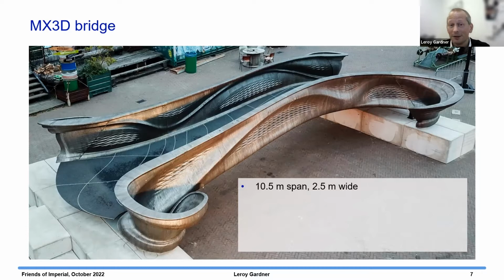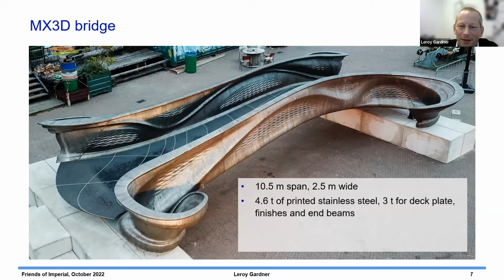It's a footbridge. It's 10.5 meters span and 2.5 meters wide. There's about 4.6 tons of printed material. It's stainless steel. And then there's an additional 3 tons for the deck, finishes and end beam, and these are essentially non-structural elements. The printing took about 12 weeks in total print time, spread over a 6-month period. Printing wasn't done at full speed because there was a bit of learning and checking as the process was going on.